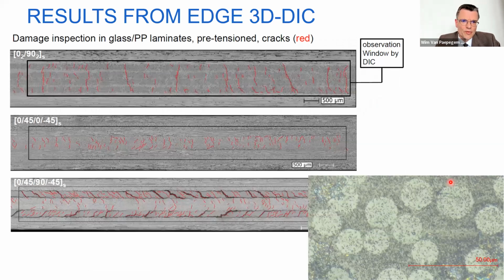And finally, again, validation. Do we trust this? So after a fatigue test, we do not run till final failure, so we stop before. And then under the microscope, Joseph in this case is the victim who manually measures all the cracks and compares the crack density with a measured one from the digital image correlation. And this way we get another verification, yes, this works.